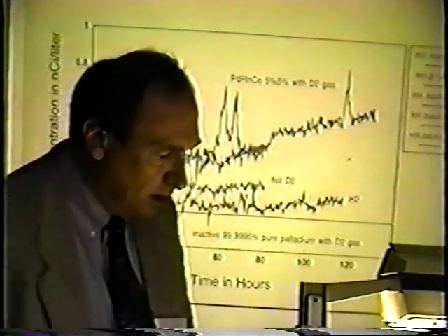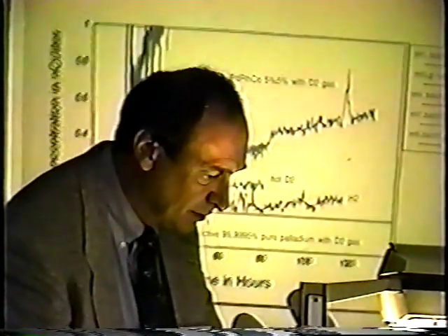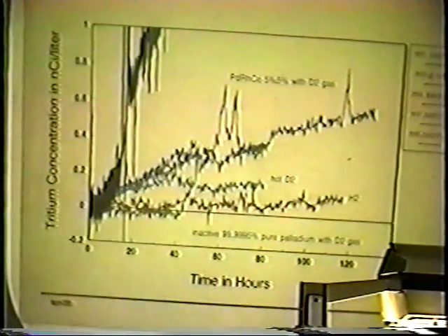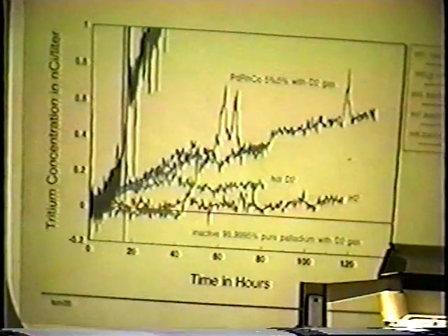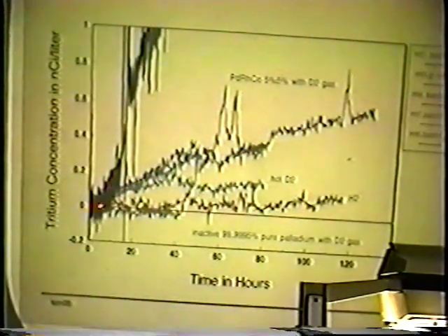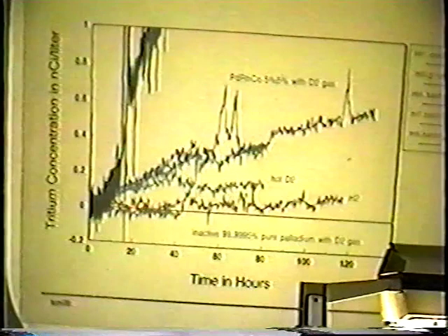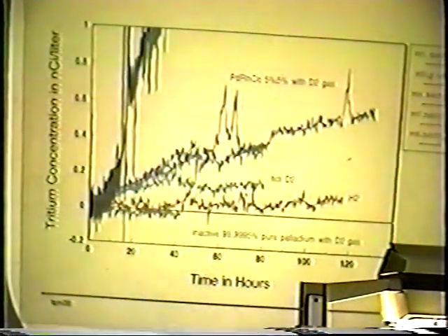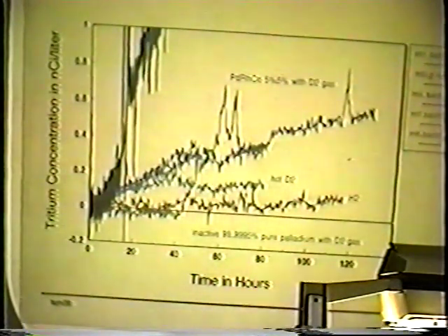Now, recently what we've done is this sort of thing, and this is again the same batch, starting off here, running it under these conditions, but it's fully hydrided, and it's fully hydrided because prior to this we spent about a week cleaning up our loop, and it turns out that after a number of these runs, and I'm not really sure why we should have something build up in the loop, but we do.